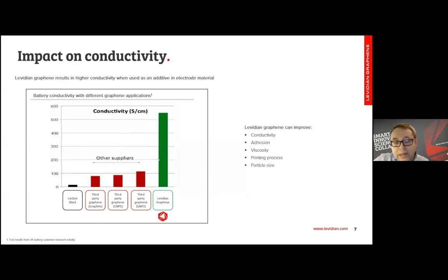That's very difficult to obtain if you are dealing with carbon black or graphite, which is exposed to other elements. So when you want to integrate an additive like graphene, you should be mindful of the other impurities that might be present, absorbed on the surface of these materials, and therefore potentially deteriorating the conductivity of the part of the battery that you're trying to enhance. So in this case, we have seen quite an interesting superior effect purely because of the way our graphene is produced and integrated into the cell.